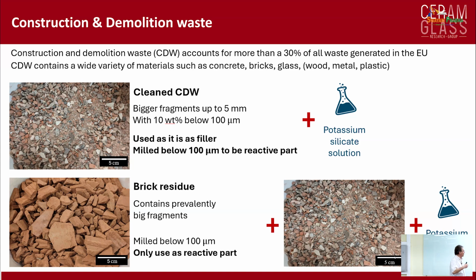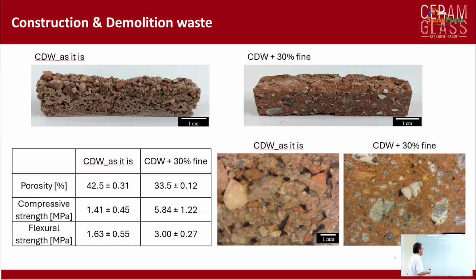construction demolition waste, or you can use a regular demolition waste that contains also fragments of concrete. In that case, of course, you are diluting the amount of reactive material in the system. And so this on the left doesn't look very nice because we simply used as-received construction demolition waste. But if we grind the material, then we can obtain better performance. This is not great in terms of mechanical properties, because if you use metakaolin, you get much better properties. But it is a good way of recuperating some waste.